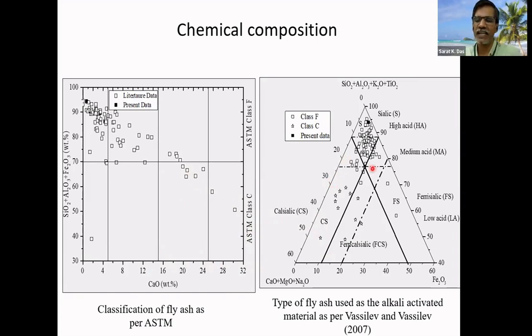So as you see this data, this will tell you also about its pH and its huge potential in future, how these fly ash can be utilized, and that will also help to get its valorization. So what I said now, we have two types of fly ash, Class F and Class C. Then if we go for the origin, mostly Class F fly ash is from bituminous or subbituminous coal, whereas Class C fly ash is from lignite base. And lignite deposits are always very less, so Class C fly ash is very less. And yesterday also, the Prof was saying Class C fly ash can be readily used because it's cementitious, whereas Class F fly ash is not cementitious, so it gets accumulated.